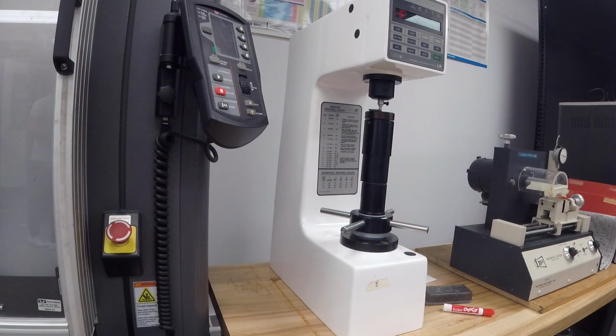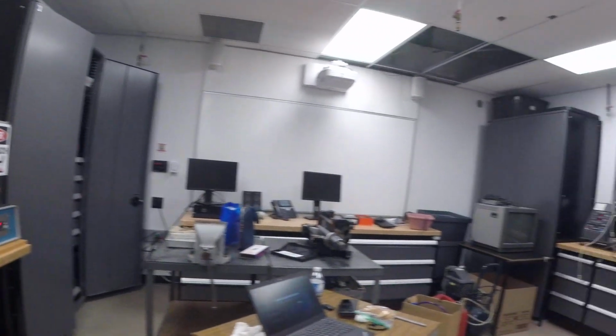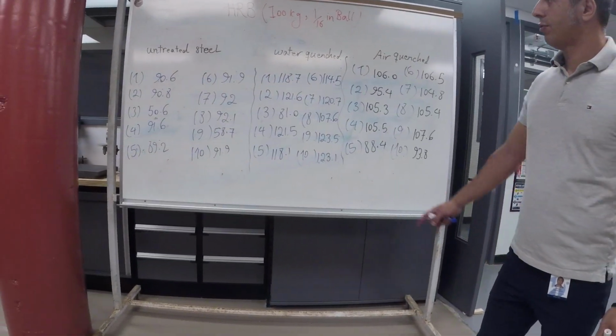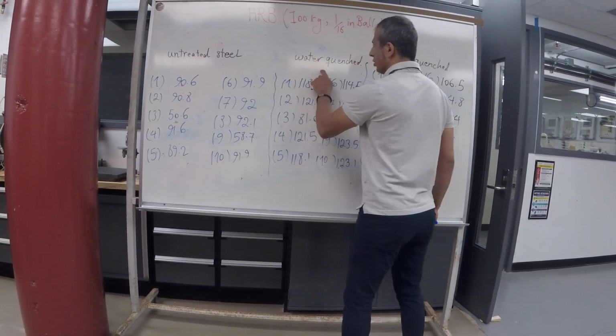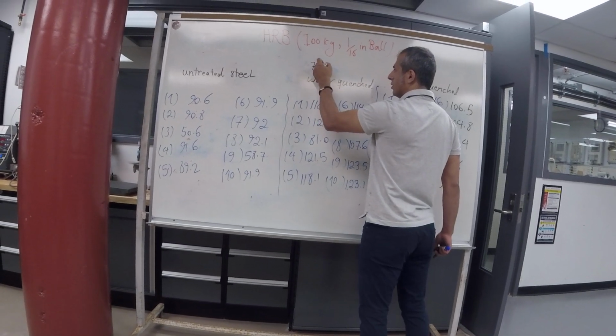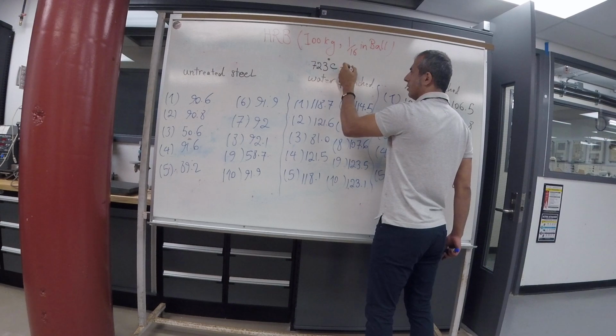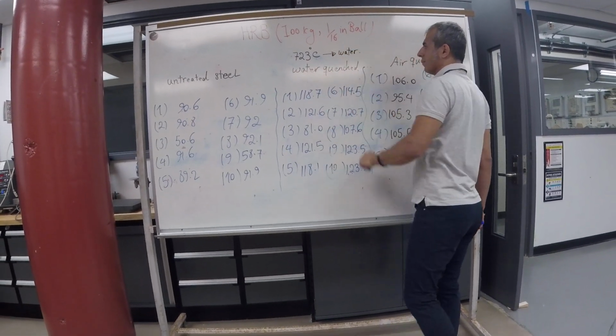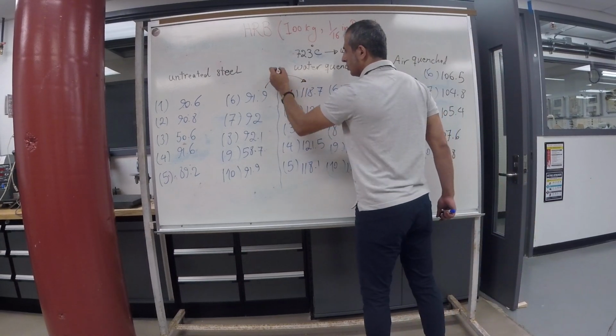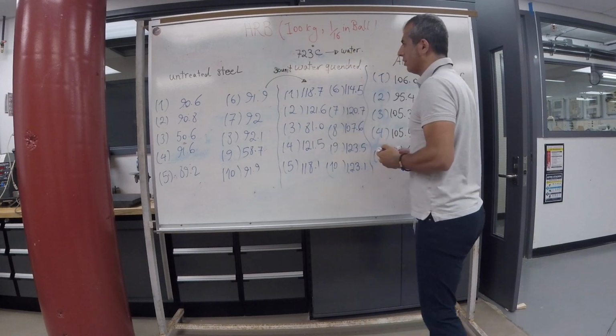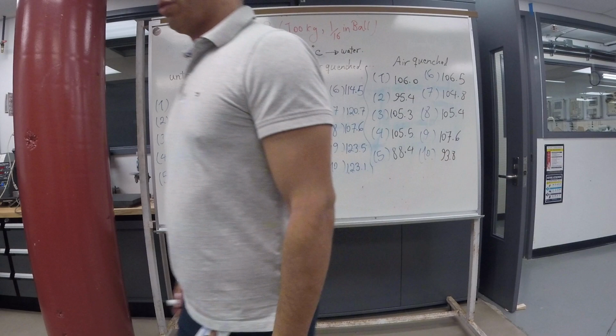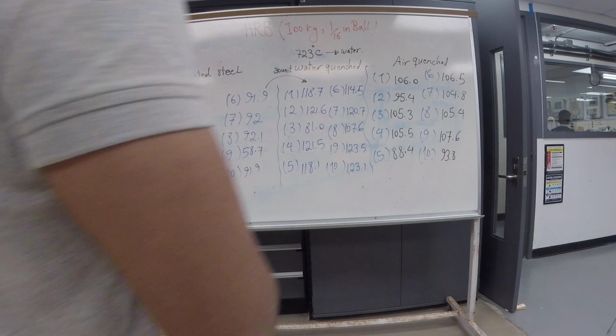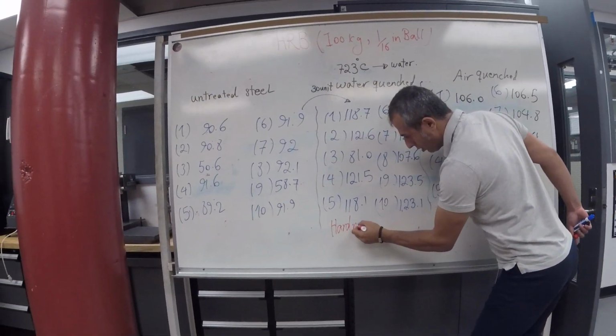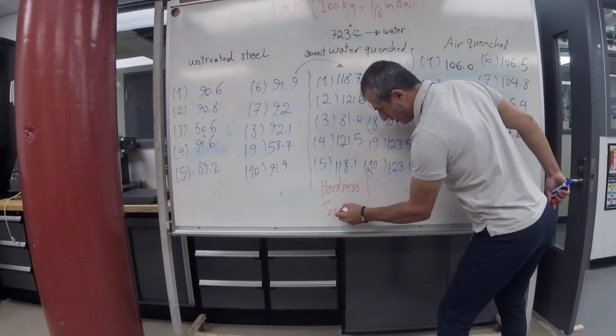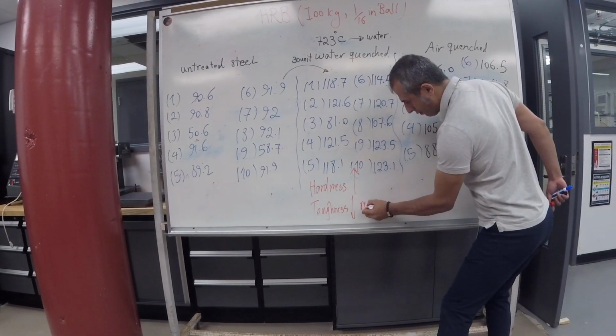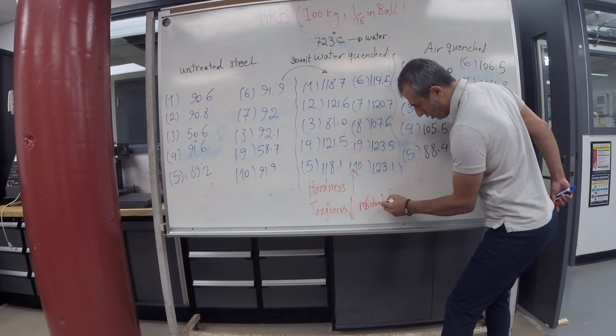So if we check right now on board, those are the values for untreated steel. As I said, 90. And when water quench, it means heat up to 723 degrees Celsius and then cool down in water. We get that 30 unit bigger. So for this one, if I want to write down, hardness increased, but toughness decreased because of residual stresses.